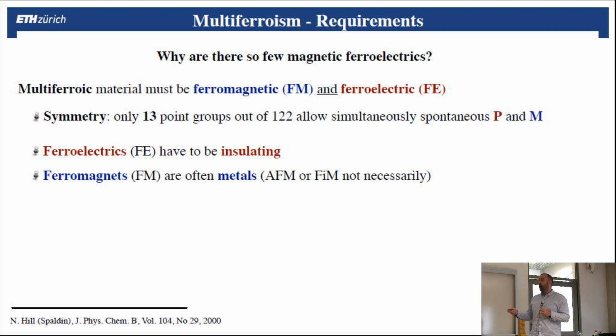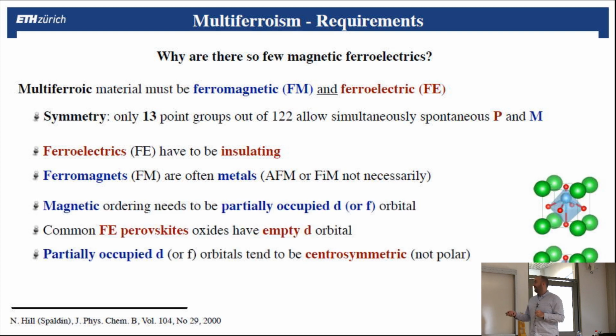On the other hand, ferromagnets are often metallic, so they are metals, which is a problem for this to go together. But further than that, if one looks at the origin of the magnetic order, to have a net magnetization in your material, you need partially occupied d or f orbitals. If you have two spins, for example, two electrons in your orbitals, they will be in the same direction. But if you now fill all the possibilities with up and down, then they will cancel out and you have no net magnetization.